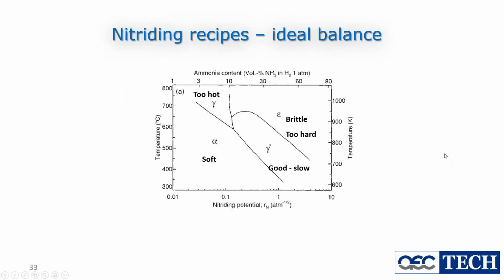As we discussed, there should be a different temperature range and different ammonia contents, or volumetric concentration, in the environment. You'll get different phases. As I said, alpha is soft, epsilon is brittle, gamma is made at high temperature. It's not made at low temperatures. And then gamma prime is good, but it's made at the lower temperature. It's slow, but it's what we want.